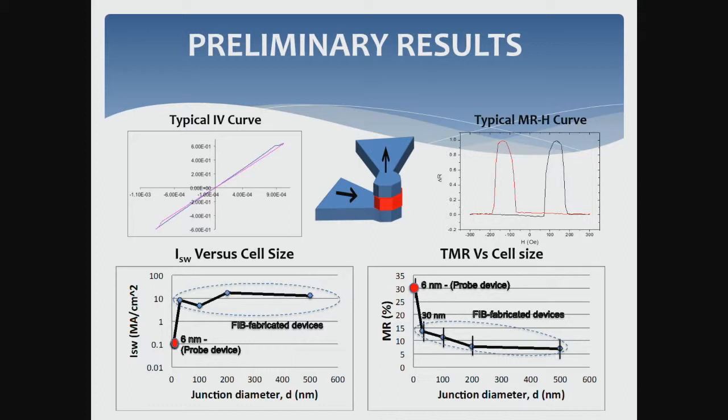Now over here is what's expected for a full magnetic loop, in which we start by saturating the entire junction, meaning both spin layers are effectively in one direction. You can define that as either up or down. And as we increase the magnetic field, we eventually get to a point where one of the layers will switch due to the difference in coercivity, causing an anti-parallel state, and then we fully saturate it again. And as we retrace the steps back, we see the exact same phenomena.